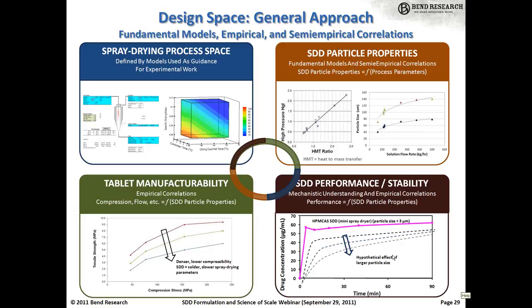So for instance, Corey mentioned the case where performance can be impacted by particle size. And then in that case, control of the SDD particle size is key, and your atomization parameters become critical to quality parameters. We won't really talk about that case today, but we're happy to go over that if you'd like to contact us in the future. The next few slides will go over a case where SDD compressibility in fact impacted tablet manufacturability. So the thermodynamic spray drying parameters became key SDD parameters.